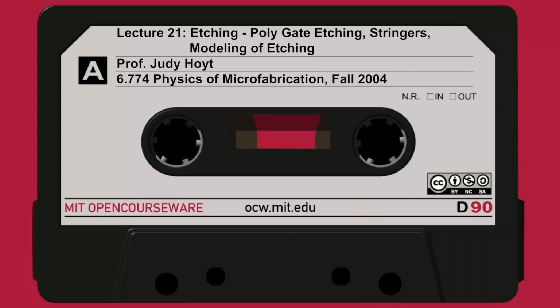And then you move to the last stabilization now, and you're stabilizing to get ready for what's called the over etch. So there's a breakthrough etch to get through the native oxide. There's a main etch, which does most of the work. Now the over etch is the amount of time you need, remember, where you've pretty much hit the bottom, but you may have stringers or other things. So the over etch typically has to have even greater selectivity than the main etch.